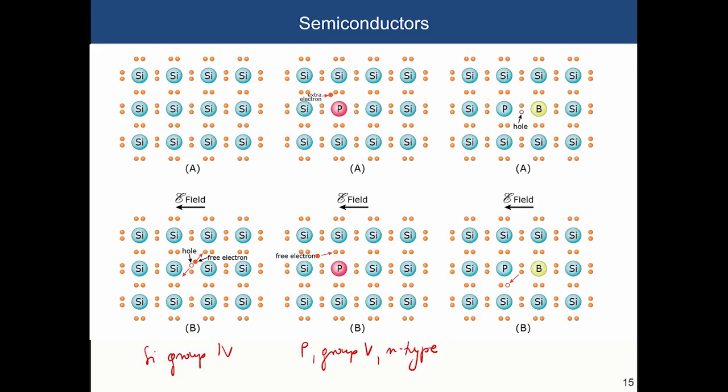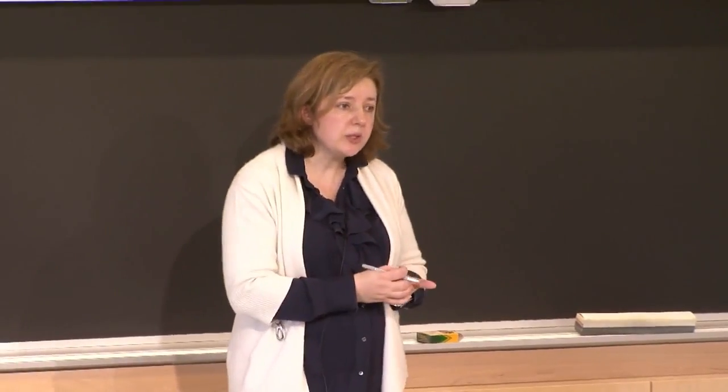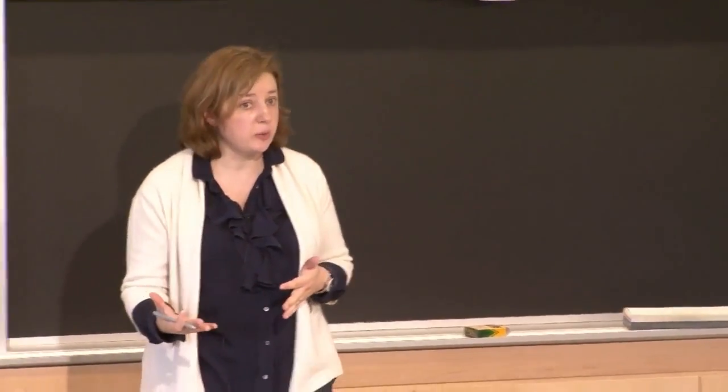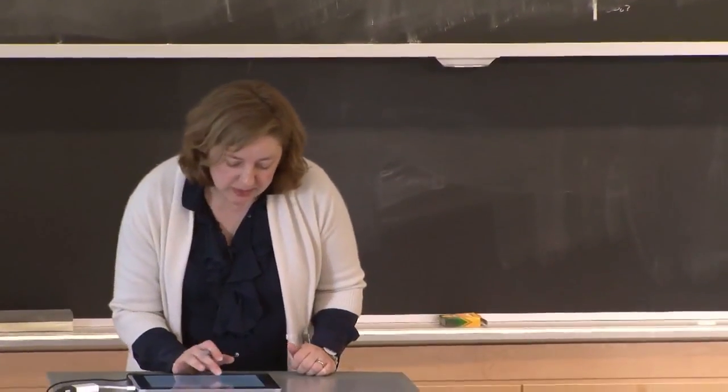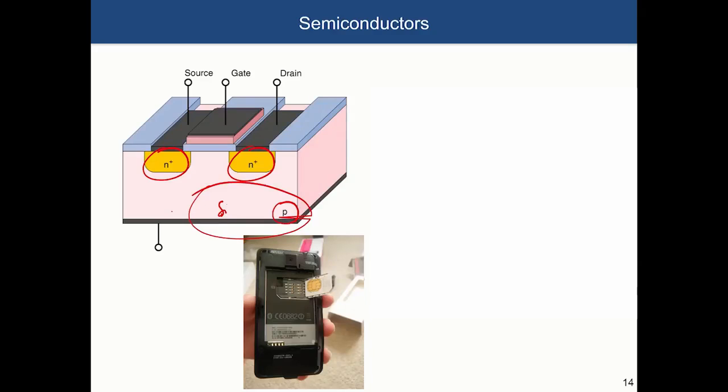And the opposite thing happens when you add, for example, boron, which is from group 3. This will result in a P-type of a material. So in other words, if you take a pure silicon, you can make it either N or P-type, depending on what kind of impurities, in this particular case, substitutional atoms you make. Okay? So again, when we come back to this picture, what that means is that in this crystal here, I have one type of dopants, substitutional atoms, and then I have completely different types of substitutional atoms that are introduced very locally